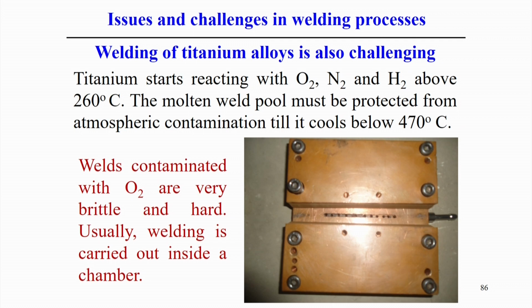This type of extra arrangement of shielding gas may not be required when you do the welding process with either plasma arc welding or tungsten inert gas welding. So that is how to protect against this oxidation problem to some extent in the welding of titanium.